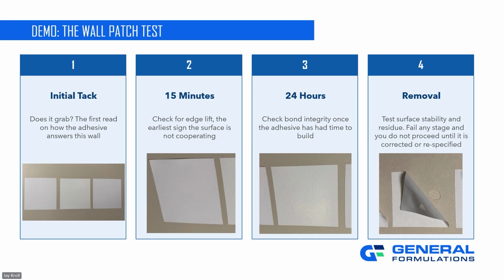After 15 minutes, we're seeing the adhesive at peak, and if you don't see it lifting or failing at the edges at this point, that's a great sign, right? And after those 24 hours, that's where we check the bond integrity. Once the adhesive has had that time to build, that wet out part again. So when you do that removal, and I recommend doing this in an inconspicuous area, we're testing for surface stability and we're testing for residue.